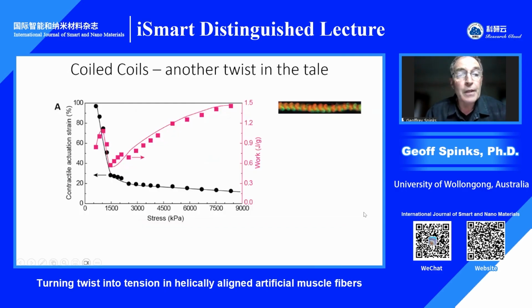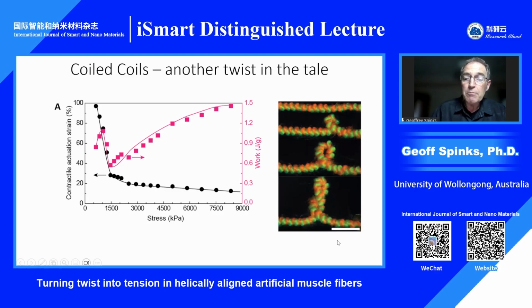these supercoils. So finally, we then took a coiled fiber, so the same polyester, polyacrylic acid twisted fibers, but now overtwisted to form these coils, and then swelled those in acid and base, and we produced again plectoneme structures or coiled coils. And this is particularly useful because what we see now, as shown by the black dots, we can get contraction strains well over 90% at still quite appreciable applied stresses of a few hundred kilopascals. And remembering as a benchmark, natural muscle produces a maximum stress of just 300 kilopascals. So we're well in that range here and producing 90% contractions.